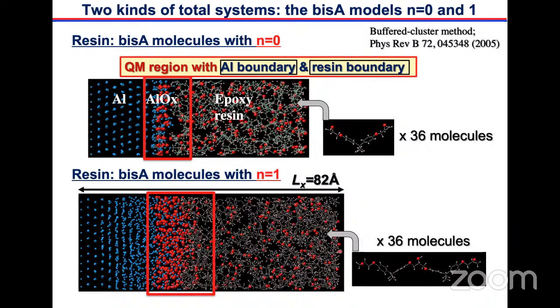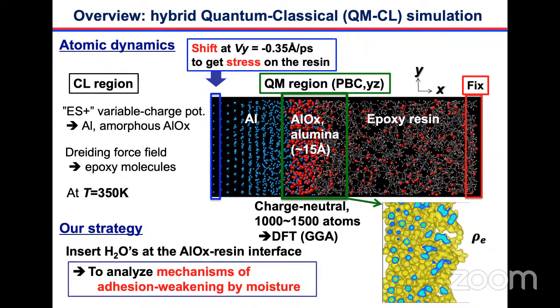In the n equals 1 case, we have a larger size compared to n equals 0, so we have to prepare a larger system. Then this red region is taken care of in the quantum mechanical way, using the DFT method. So this is the overview of what we do using the hybrid quantum-classical simulation. This right end region is fixed, atomic positions are fixed, and this left end region of aluminum is gradually shifted at constant speed in the minus direction to get the stress on the resin. Then we monitor the stress on the resin and can get the maximum value of the stress. This corresponds to the maximum adhesion strength of this system.